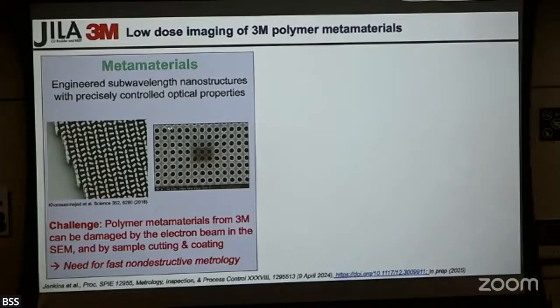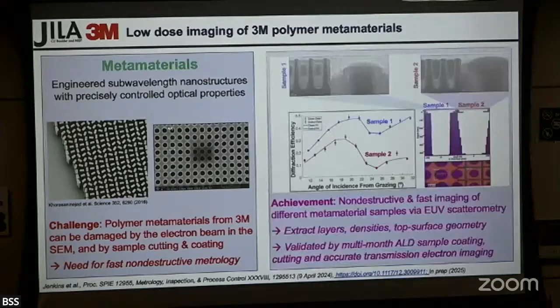We would like to gather as much of the light as possible, but they're tough to image because the way they work is that they're made out of plastic, very complex structures. They have to have little holes that are smaller than the wavelength of visible light, so you can't use a visible microscope. And if you put it in a scanning electron microscope, the high energy electrons tend to partially melt the polymer metamaterial. So that was the challenge we were trying to overcome.